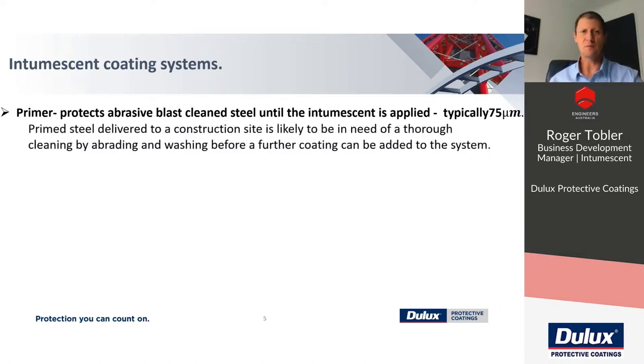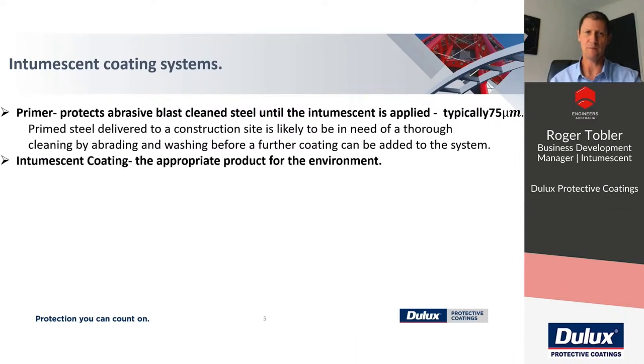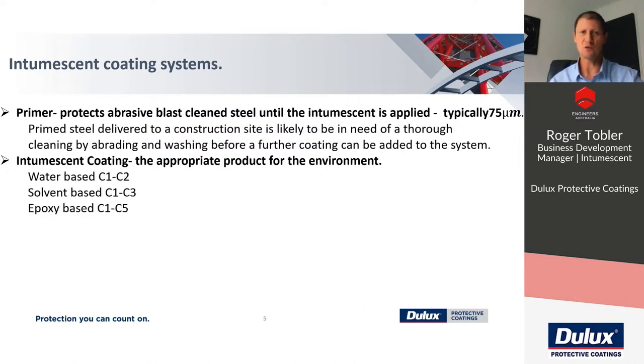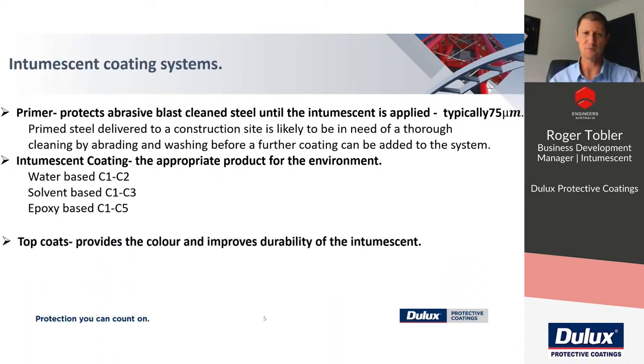The primer does need to be clean, and often on a construction site there may be cement and a whole lot of debris and contamination on the primer. So yes, you are going to have to wash it, and this may require a good abrading before you apply the intumescent coating. The intumescent coating will be the appropriate intumescent coating for the environment. Water-based C1 to C2, solvent-based C1 to C3, and epoxy if it goes up to a C5 environment.